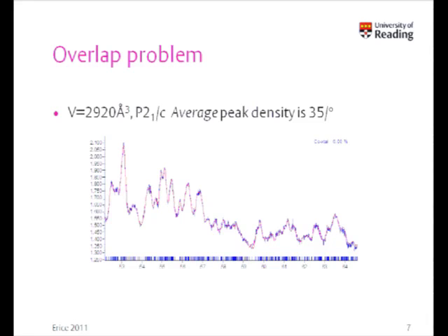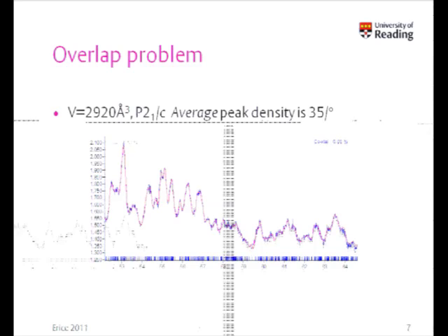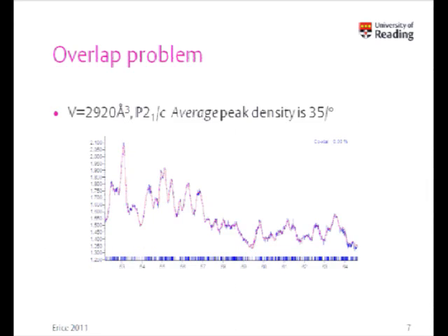And so this is a fundamental problem for organics, particularly because it's this high angle area that's going to pin down the fine detail of the structure and tell us that our structure is being fitted properly. As we saw earlier on, it's actually often possible to fit the low resolution part, the low 2 theta end of a pattern, quite happily. Peter showed it in indexing: index a subset of reflections, and then things start to move out of register as you move higher up. It's exactly the same with organic materials, relatively easy to solve at low resolution, not so easy to pin down the level of detail at high angle.